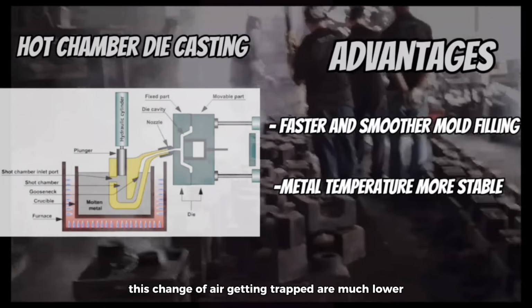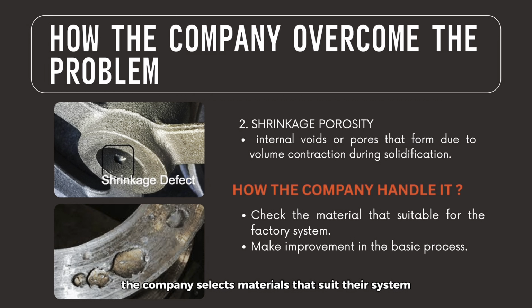This defect refers to tiny gas bubbles trapped within the metal during solidification, weakening the final product. To solve this, the company takes preventive measures such as using clean and dry metal alloy to avoid hydrogen gas formation. They also carefully control the smelting temperature to reduce the risk of overheating and gas entrapment. Another issue is shrinkage porosity caused by metal contracting during cooling. To address this, the company selects materials that suit their system and continuously improves their casting process for better solidification.